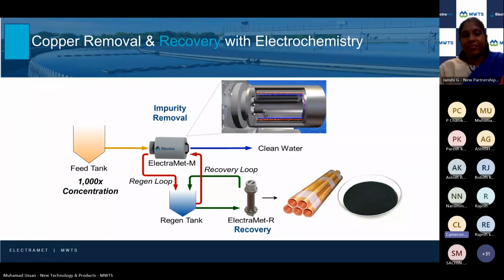And so how does the ElectraMet process work? We have a two-step process. Coming from the feed tank along this blue line, we remove the metals inside of our electrochemical reactor. We go from the dissolved metal and plate it out on our cathode. Once the cell is saturated, we have an internal closed loop process, very indicative of a clean-in-place type process. We use an acidic media, a regeneration solution, that collects the metals from our reactor and concentrates them up in this regen tank. That reactor is now available to use again to remove more metals.